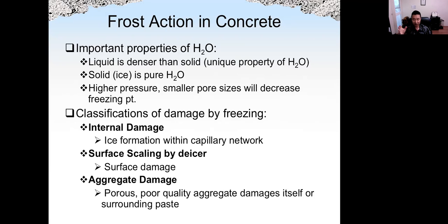And then let's look at the freezing damage possible in concrete. So the first one is internal damage, which is ice formation within the capillary pores, so within the cement paste. We also have surface scaling, which is the damage only on the top surface of concrete. This is due to de-icing solution. During winter, to melt ice, people will put a de-icing solution. So that kind of salt will decrease the melting temperature, the freezing temperature of ice. We use that commonly during the winter for the concrete pavement. So that will only cause surface damage in the concrete. So we call that scaling damage.